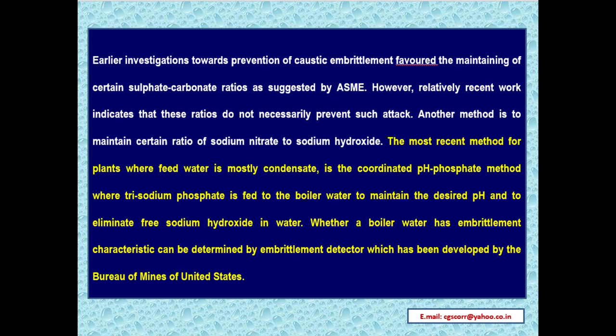Earlier investigations towards prevention of caustic embrittlement favored maintaining certain sulfate carbonate ratios as suggested by ASME. However, relatively recent work indicates that these ratios do not necessarily prevent such attack. Another method is to maintain a certain ratio of sodium nitrate to sodium hydroxide. The most recent method for plants where feed water is mostly condensate is the coordinated pH phosphate method, where trisodium phosphate is fed to the boiler water to maintain the desired pH and to eliminate free sodium hydroxide in water.